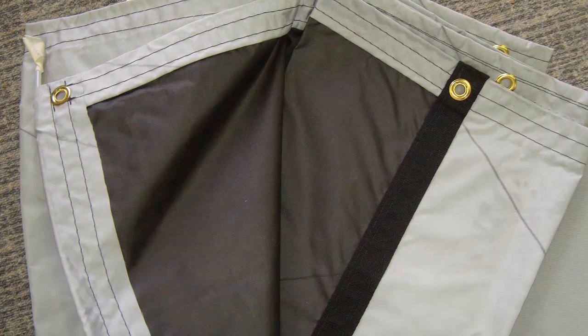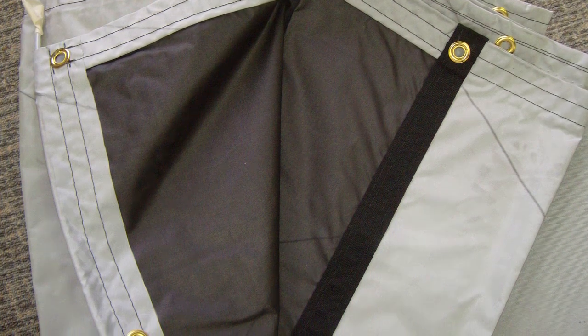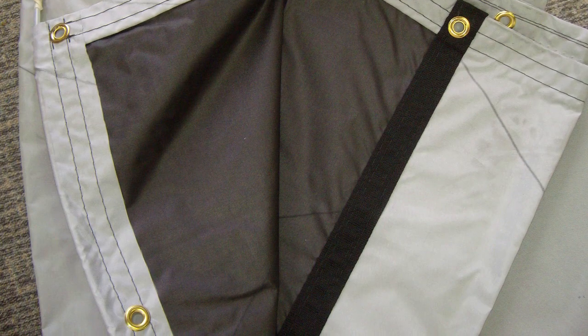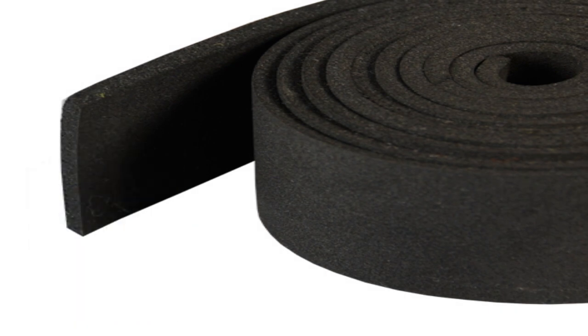The pressure bladder is made of nylon coated with urethane, surrounded by nylon neoprene composite. The urethane is non-permeable, so it holds air in. However, the urethane has very low heat resistance and has a dangerous melting point of 50 degrees Celsius, which would cause problems when encountering direct sunlight. The nylon adds strength, something the poor balloon needed, with a yield strength of 30 to 55 megapascals, which compares with the tensile strength of 44 megapascals for urethane and about 15 megapascals for neoprene.